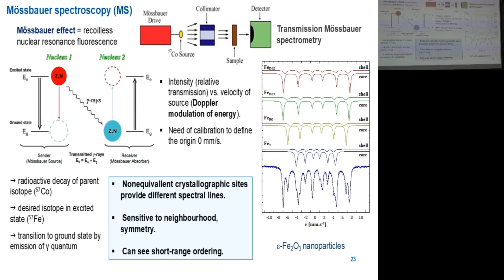Well, Mössbauer spectroscopy. This is kind of a special technique which is unfortunately not as common as it should be in the papers on magnetic nanoparticles, because the majority of researchers are working with iron oxides, and they are working with magnetite or maghemite or some mixtures between that, and they should analyze the samples correctly in terms of the real oxidation state of iron and real composition. And the Mössbauer spectroscopy, or 57 iron Mössbauer spectroscopy, is the only way how to do it, I would say.